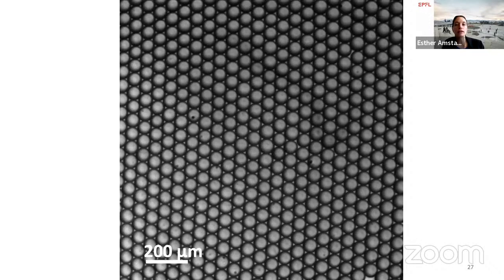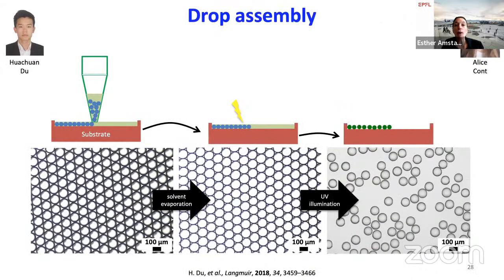Because the drop size is independent, or nearly independent, of the fluid flow rates, you get very well-defined drops at relatively high throughput, up to 100 milliliters per hour, depending on the viscosity of the interface. Now, what many people do with these drops is convert them into microparticles by having an aqueous phase that contains reagents and some sort of initiator, then initiating the polymerization reaction, for example, through illumination with UV light, and then you transform these drops into particles that have similar sizes as the drops.